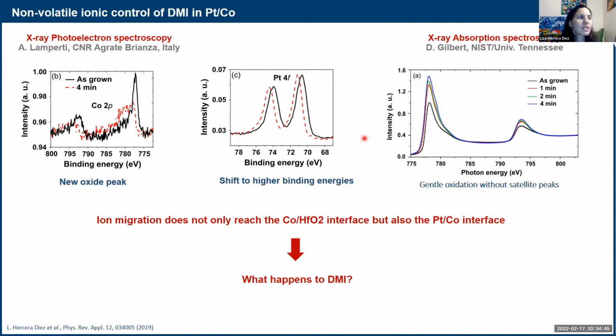So this was an interesting point for us because we wanted to make sure to reach this bottom interface. The fact that something was going on with the platinum was an indication that the ions were going relatively far. And actually, I'm not going to show it today, but Dustin Gilbert, our collaborator from the US, also performed neutron scattering experiments. And then we could reconstruct the depth profile of our stack and see that there were even changes in the platinum silicon oxide interface at the very bottom of the stack. So the ions can indeed go very far. This is really what we were looking for, some evidence that the ions could really go and interact at the cobalt platinum interface. So this was the moment to go and see what happens to DMI.